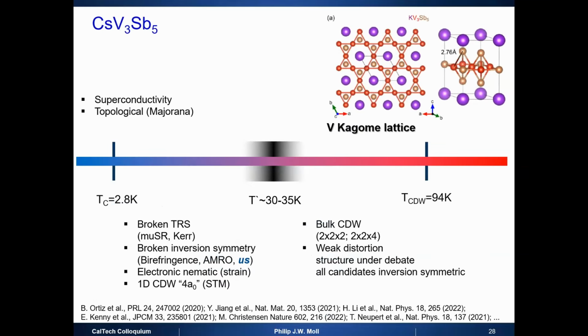We're working on this particular compound, cesium vanadium antimony, which is a Kagome layer of vanadium atoms. Then there's the interstitial of antimony, and they're separated now by potassium. You can put cesium in here. Potassium, we mostly work with cesium because it's the cleanest. And now what this system does, it is a Kagome up to about 90 Kelvin. There is a charge density wave transition. We all agree on this transition. They slightly distort. There's superconductivity at low temperatures.